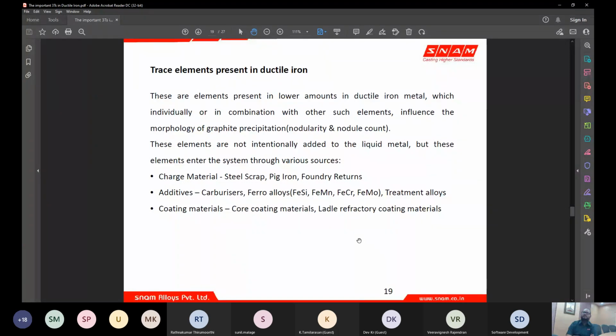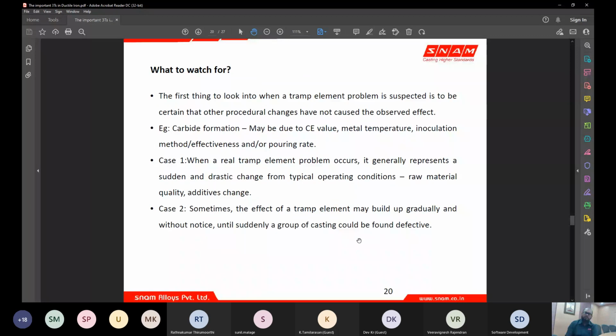What do these elements do? They start impacting the nodularity, nodule count, and other microstructure constituents, which is going to decide the uniformity of your mechanical properties. So what should we look for? What to watch for? The first thing to look into if we have a tramp element or a trace element problem is whether all the other procedures being followed are constant. So for example, if you suddenly observe carbide formation, to attribute that carbide formation to a tramp element or trace element, we should first ensure that our time, temperature, and other chemical composition which we can control by ourselves are already in control or not.